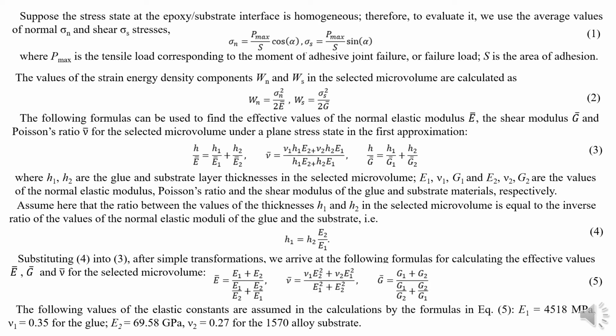Formulas 3 can be used to find the effective values of the normal elastic modulus, the shear modulus and Poisson's ratio for the selected microvolume under a plane stress state in the first approximation, where H1, H2 are the glue and substrate layer thicknesses in the selected microvolume. E1, E2, v1, v2, G1, G2 are the values of the normal elastic modulus, Poisson's ratio and the shear modulus of the glue and substrate materials respectively. Assume here that the ratio between the values of the thicknesses in the selected microvolume is equal to the inverse ratio of the values of the normal elastic moduli of the glue and the substrate. Substituting 4 into 3, after simple transformations we arrive at formula 5 for calculating the effective values for the selected microvolume.